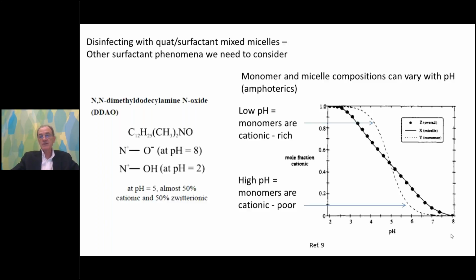And what we see is the monomer and the micelle compositions do not have to be the same. At rather low pH, the monomers are all cationic. They're cationic rich, much higher amount of cationic monomers. And then at high pH, we have exactly the opposite. Now the micellar reservoir, the fraction of cationic molecules in the micelles is a lot greater than the monomers.